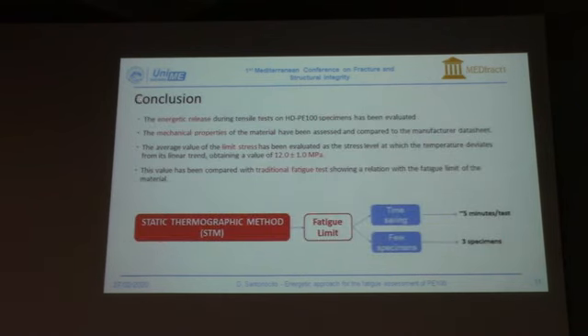Finally, it is important to note that with very few specimens, 3 specimens, and 5 minutes per test, we can obtain in a very fast way a good estimation of the fatigue limit.